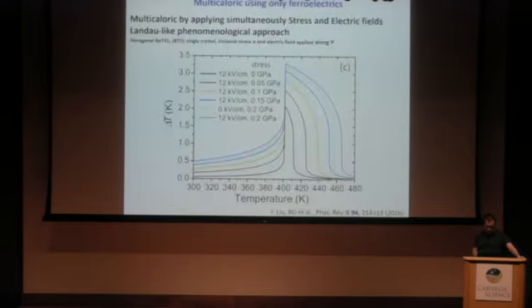And actually, Murata is working a lot now in this direction. Murata company. So what we can also do, ferroelectrics also have an elastic transition. We know that once the polarization appears in the system, there is a distortion of the system. Therefore, we can not only apply an electric field, but we can apply a stress on the system. And if we combine both, we can enhance the global delta T of our system. So it's also a way to play with the so-called multicaloric aspect, which I guess might be very interesting to exploit or to explore in the next years.